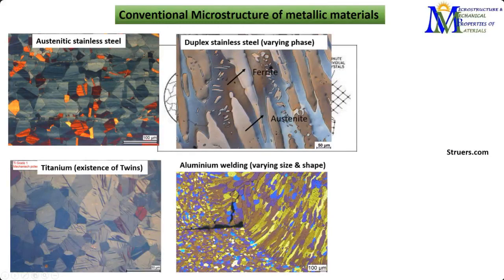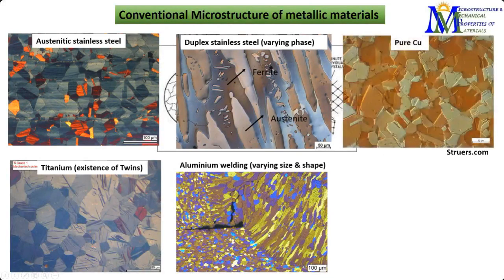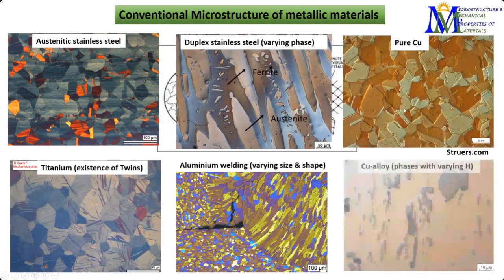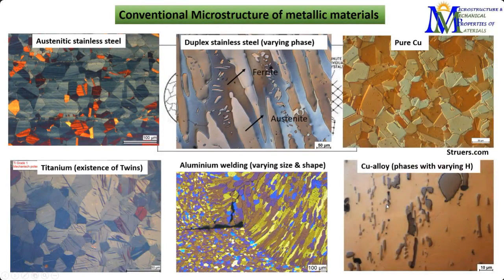This is an aluminum welded structure where we see different variation of grains - columnar grains and equiaxed grains of different orientation. This color signifies the different orientations that the grains are aligned. This is a pure copper one, and this is the copper alloy having different phases with completely different hardness. So this is typical of what we get from conventional systems.